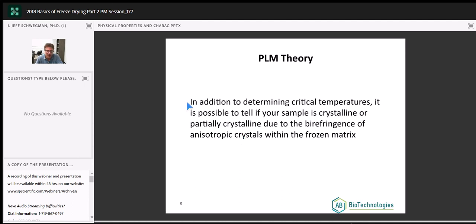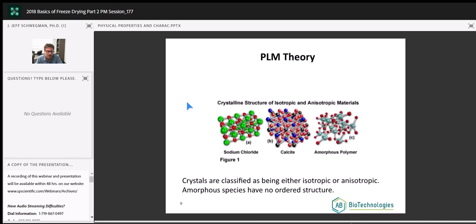So a little bit about polarized light microscopy theory. In addition to allowing us to determine critical temperatures, collapse temperatures, it also gives us an idea of the crystallinity of our formulation. So basically, we talk about something forming a crystal. An amorphous material forms no crystals. It's not going to refract the light. We don't see much of that. With birefringent crystals, isotropic crystals, and anisotropic crystals, we see vast differences.